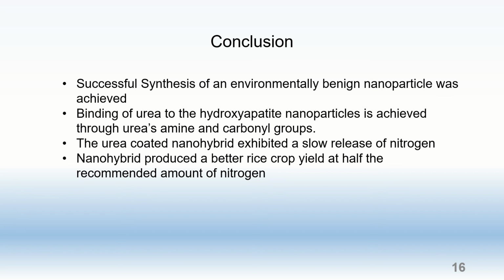So to conclude, the experiment showed that an environmentally benign urea-coated hydroxyapatite nanoparticle was successfully synthesized. It was revealed that the urea interacted with the hydroxyapatite nanoparticles through its amine and carbonyl groups to produce a nanohybrid that exhibited a slow release of nitrogen to produce a better rice crop yield at half the recommended amount of nitrogen.